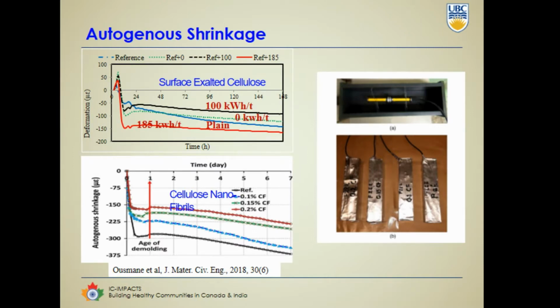And there is 185 kilowatt hour. You will notice very quickly that at 185 kilowatt hour, when I have given more energy in fibrillation, the results don't look as good. It means it's actually shrinking more. And if you look at this 100 kilowatt hour, that seems to be the optimal fibrillation that you require, and there's no need to spend more energy in producing this product, which has got greater fibrillation than what we absolutely need. And if you look at those 5,000 kilowatt hour nanomaterials that I was talking about, you will notice that its performance is either similar or worse than some of our fibrillated material, which means you really do not require the nanofibrillation for the purpose of actually providing internal curing.